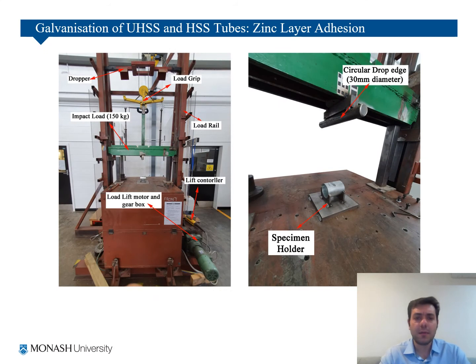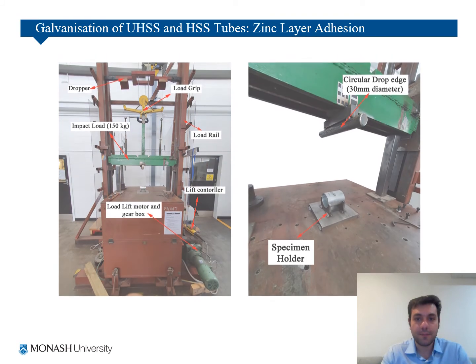Then we conducted some experiments to see if the coating behavior of the galvanizing coating is changing after being sandblasted, or for different dipping times. As you can see here, we have different small tubes, and we have a small regular impact rig. So we conducted some impact tests on different tubes, and these are the results.